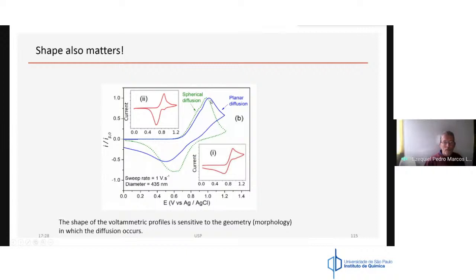And finally, what was interesting to see for this system is that depending on the type of diffusion, you get different types of voltammograms. These are simulations. If you have spherical diffusion, you have a voltammogram with a peak that runs very rapidly to zero. In the other case, you have planar diffusion, and you have a drop of the current which is much slower. Well, I think that this type of behavior explains the different behavior that was found in the experimental cases that I have shown before.